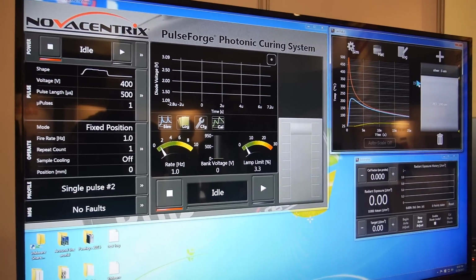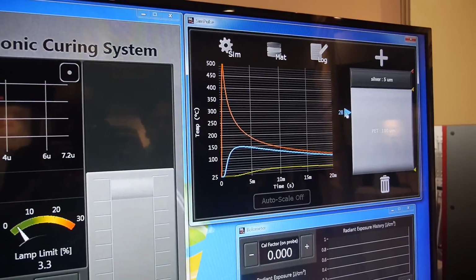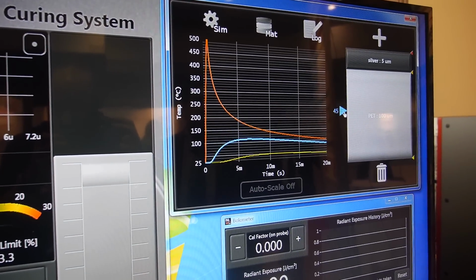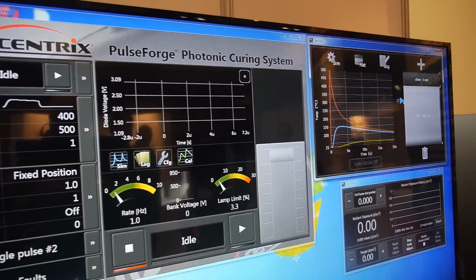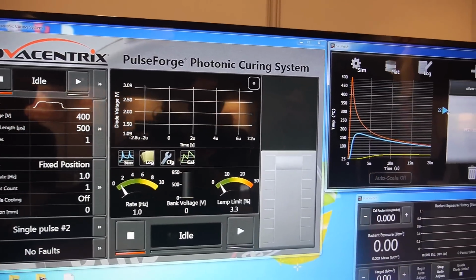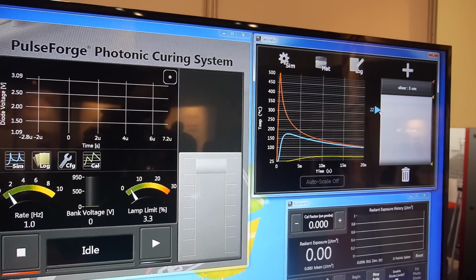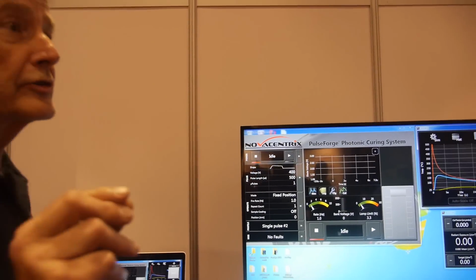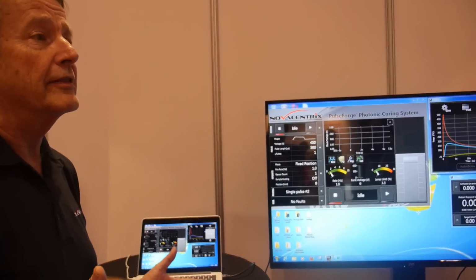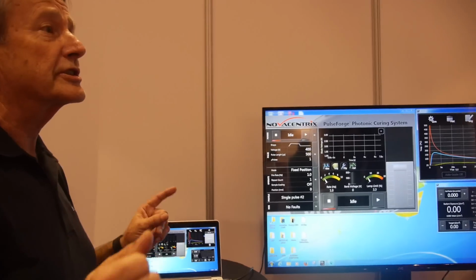If you look at the blue line here, you will see that as I move this down, this is showing exactly what the temperature is through this stack at every given level. And you can see that only going down 20 microns or so, the temperature never reaches more than a third of what the maximum is. That's the real special feature of PulseForge, in that it allows the substrate to act as the stabilizing agent. That allows us to process something at high temperatures on a temperature-sensitive substrate without that substrate distorting, so you can run it through a web. It provides the image stability that you need to make a quality product.